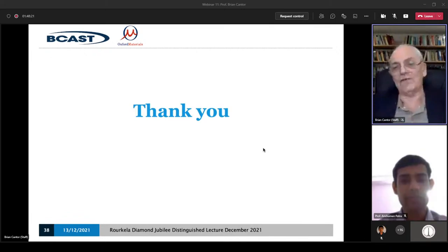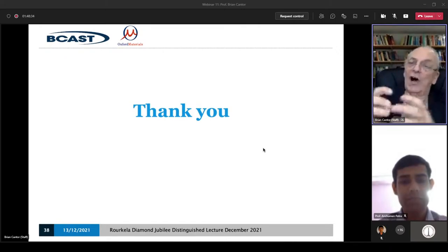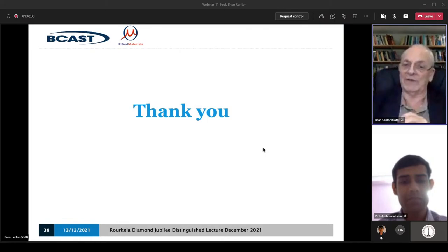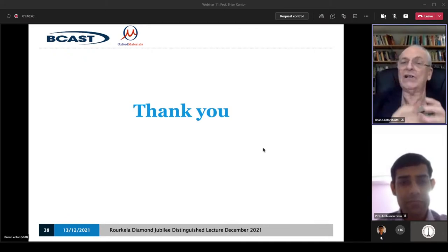So if you take what's known as the Senkov alloy, which is the equivalent for body-centered cubic, it's vanadium, niobium, tantalum, tungsten, molybdenum, in equal proportions. It's the sort of core of an enormous region of body-centered cubic phase space. Much less is known about it, much, much less.